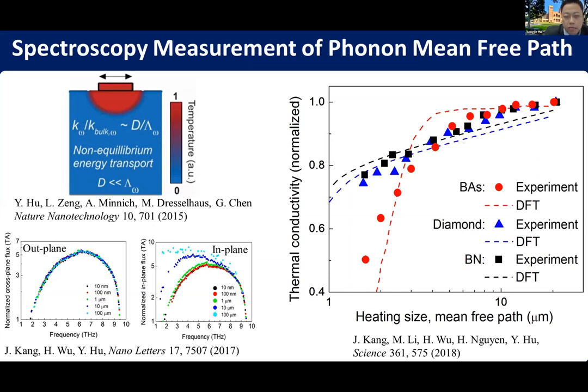So we applied this spectroscopy technique to boron arsenide, diamond, and cubic boron nitride, and made the size-dependent thermal conductivity plotted in the right figure. As you can see, when we reduce the heating size from 100 micrometers down to 1 micrometer, the thermal conductivity of all 3 materials reduces as expected due to the ballistic thermal transport.